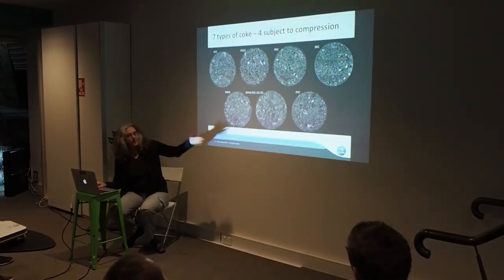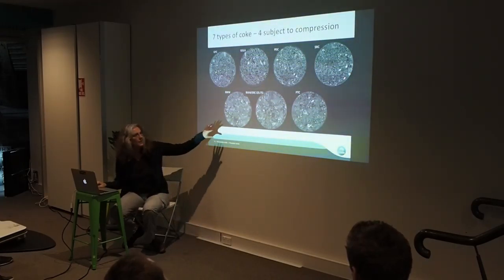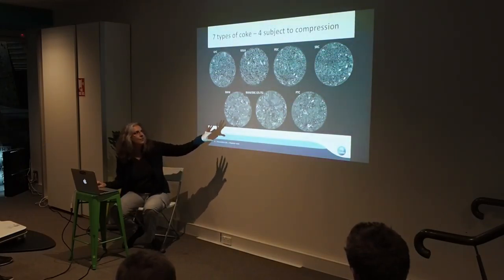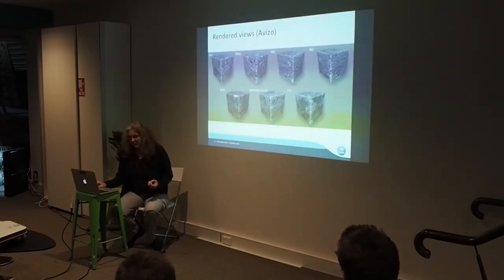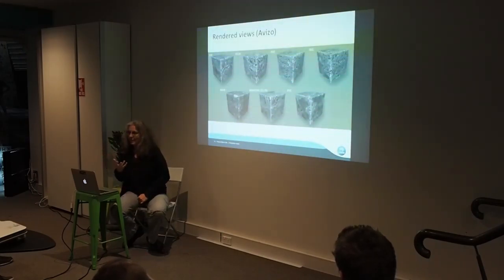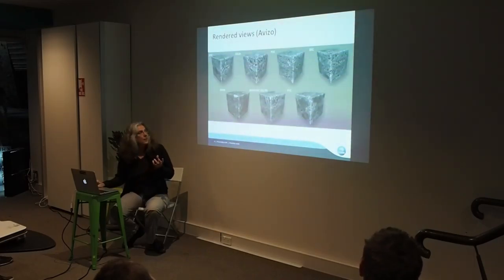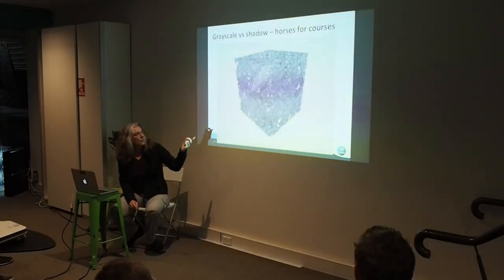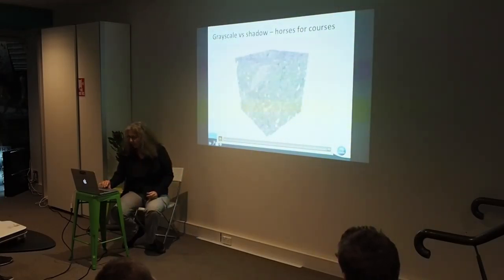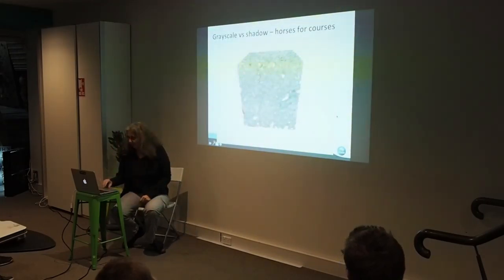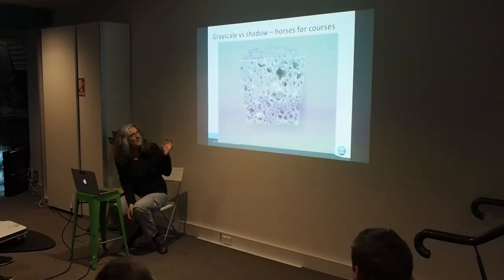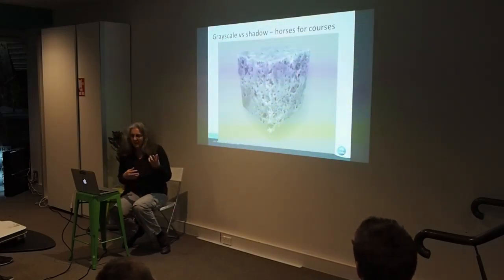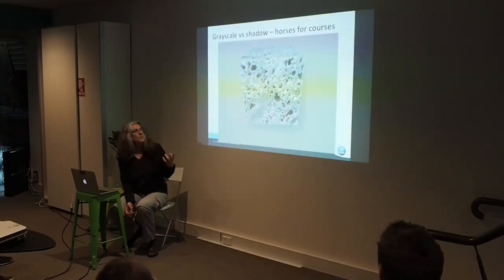So this was visualising coke. These are cross-sections of coke samples — this is just how it comes out from the mathematical reconstruction, with grey levels. My colleague wanted us to render it for him, so we do these rendered views. A difficulty we have is that rendering — you have to choose what features you want to highlight, because you're not just trying to make a pretty picture, you're actually trying to convey something scientifically. Some of these samples have very variable density, and a greyscale render shows that up well, but it doesn't really show the holes. The alternative with shadowing shows the holes much better but messes up the greyscale. So it really depends on what features you're trying to bring out and what story you're trying to tell about your sample.